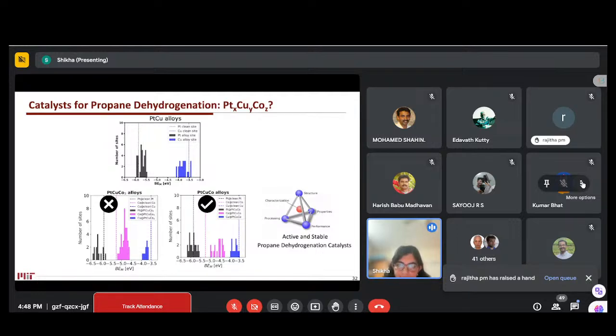But okay, we have high activity here, but the problem in experiment was that at high temperature, they could see that the alloy is not very stable. They could see distortion of the particles. So they now want more stability of the alloy system at a higher temperature. That's why they want to add cobalt and see the effect of the cobalt. When we add cobalt, how much cobalt should we add to balance our platinum copper alloy? Copper will anyway reduce the cost very significantly. Now the issue is to have good stability.